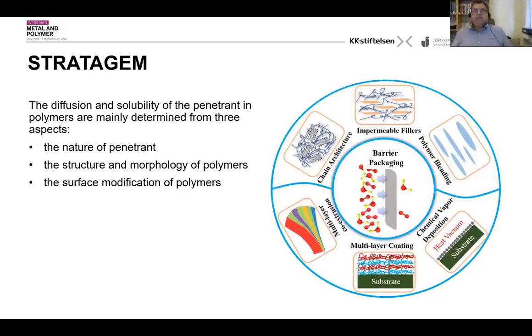Another way of improving the barrier properties of the polymers is to play with the molecular architecture of the polymer. Since we know that the diffusion in a polymer is a time-dependent process, if we can delay the diffusion of the migrating species into the polymer, we can improve the barrier properties of the polymer. Polymers are either amorphous or semi-crystalline in nature. Amorphous polymers have a lot of free space, called free volume, in their molecular structure, which allows the molecules to penetrate easily through the polymer barrier films.